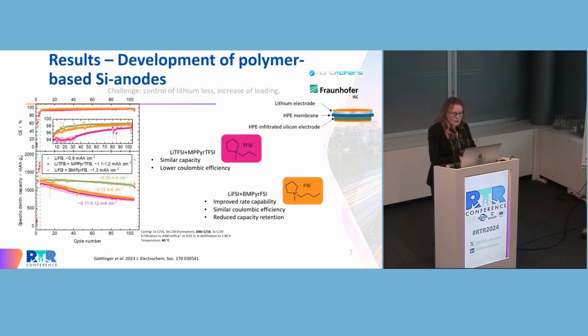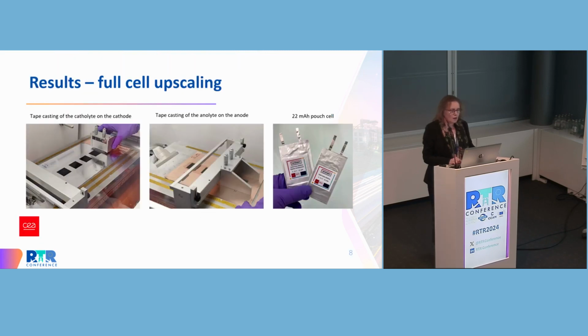We have tested different lithium salt, and in thin electrode, we obtain a good stability up to 100 cycles and a large capacity, so a reduced capacity loss. The value obtained is more than 1,500 milliampere hours per gram in this case, with the LiFSI materials and ionic liquids. These are the two formulations that have been retained for the fabrication of full cell.